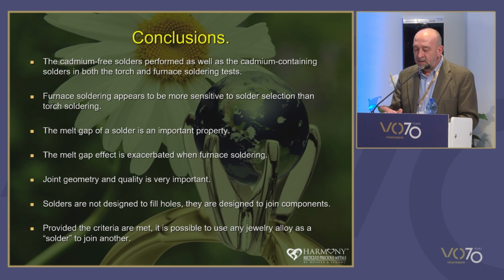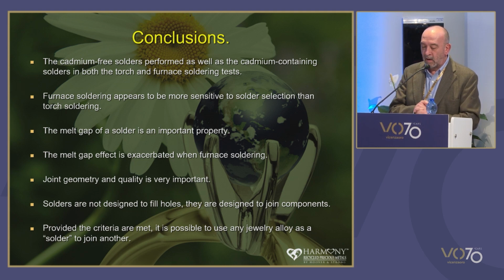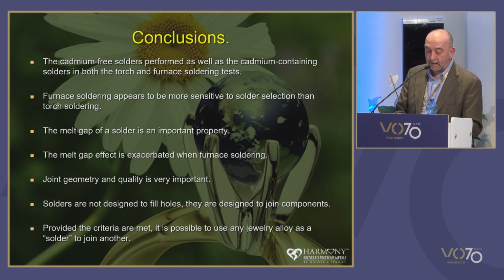So it's particularly relevant when we're looking at joint geometry, or lack of, as the case may be, and provided the chemical and physical properties of a jewellery alloy meet the criteria for wetting, elemental compatibility, and the melt gap is sufficiently narrow, it should be possible for any jewellery alloy to be used to join another one. And our final test demonstrated this.